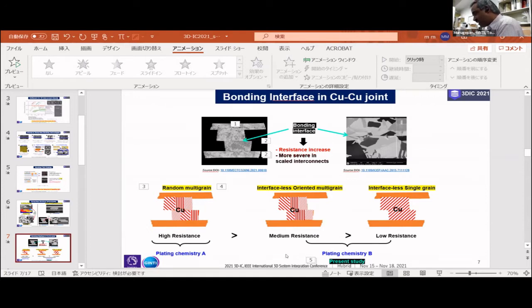So the present study aims at how we can improve this. Of course, our ultimate aim is to get a single grain of copper between your top and bottom. But if not, even if it is multi-grain, we would still like to create a structure where your top and bottom copper grains are the same, aligned, and it just has single resistance over here. So how can we do this? We go for a different plating chemistry by which we are able to increase our copper grain size as well as copper orientation.